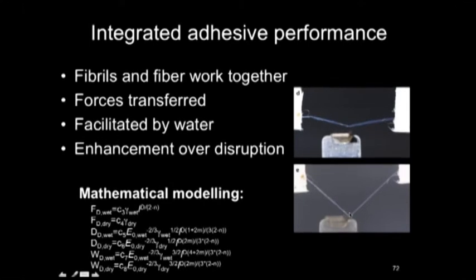And we use the mathematical model. I'm not going to explain this because it's quite complicated, but it further illustrates and supports our conclusions here of mechanical plasticization, increasing mechanical work, as well as demonstrating the axial fibers' involvement and contribution to the overall composite material. So this may be somewhat of a novel mechanism, at least in this type of silk. It may also be evidence of cave adaptation for spiders, not just glowworms, of their biomaterial to these kinds of environments.